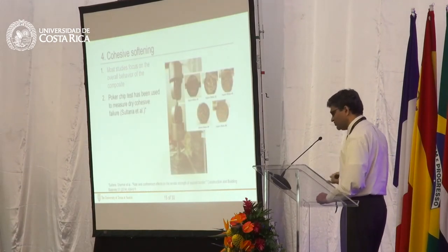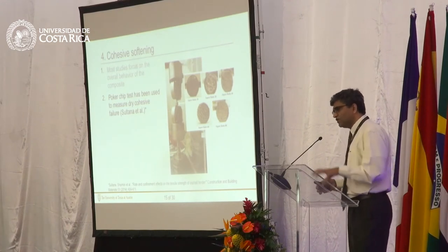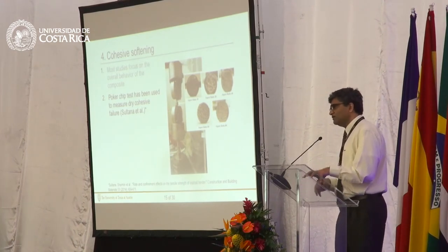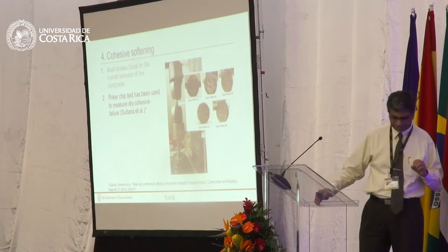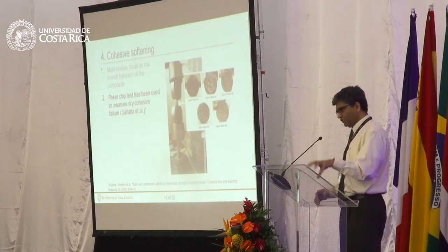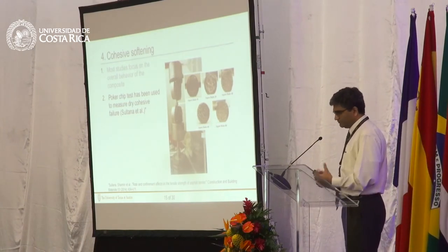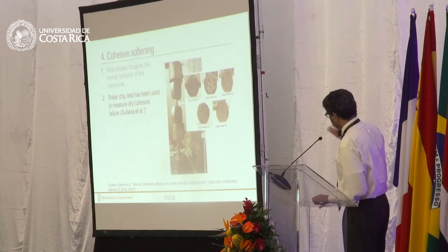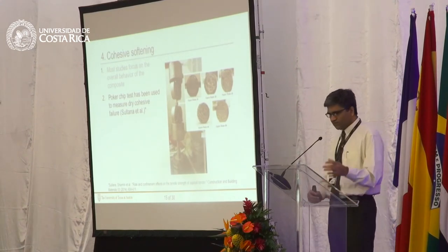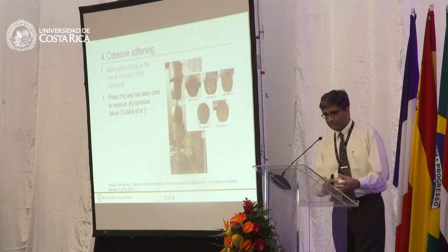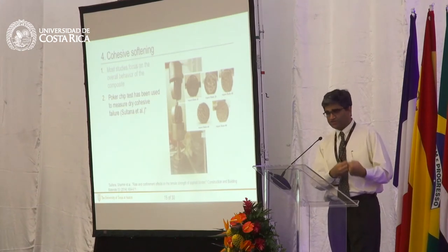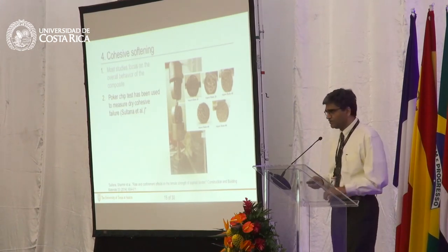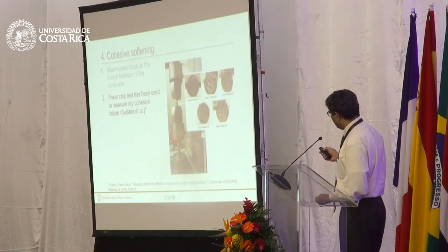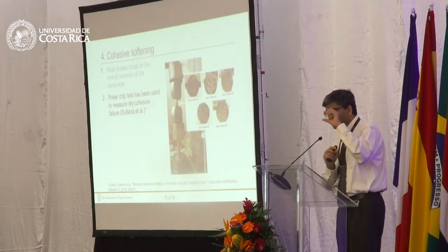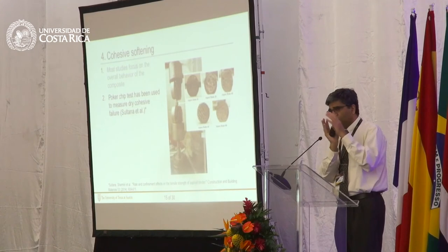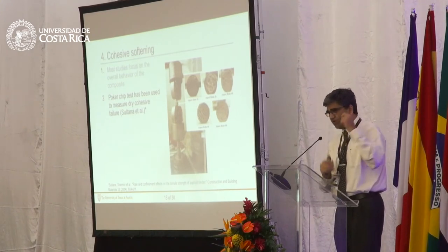Ideally, though, what you want to do is isolate the effect of binder. So a number of these tests have also appeared where the simplest name I would give is this poker chip test. Earlier today, Jeffrey was talking about strength tests where you're measuring the failure capacity of the material. The poker chip test is called a poker chip because you really have a sandwich of a thin film of bitumen between two metal plates and you pull on it.